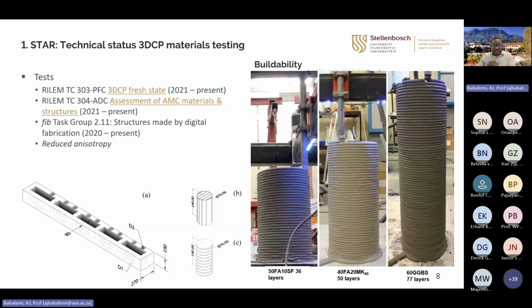So going forward with printing, typically when we develop our mix formulation and print, we would normally check for the buildability. So hardening properties are tested using cylindrical samples, but also buildability up to 1 meter within roughly about an hour. This is a nice print with 50% fly ash and 10% silica fume. 36 layers was achieved. And then this is 40% fly ash replacing cement, plus 20% metakaolin. And then with 60% slag, it could go up to 77 layers.